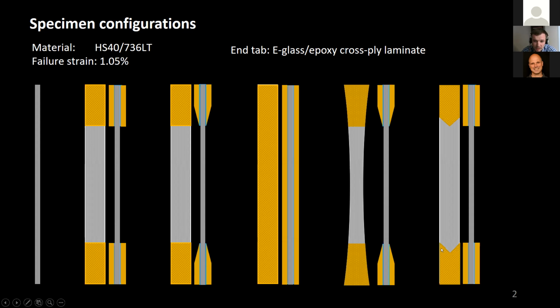And then something that was a little bit more exotic that you don't see that often in the literature with arrow-shaped end tabs. So these tabs are designed in such a way that here the length from this part of the tab to that part is always equal to 150 millimeters. So the volume we're testing is the same as in some of these other specimens, apart from this where the gauge volume was a little bit different.